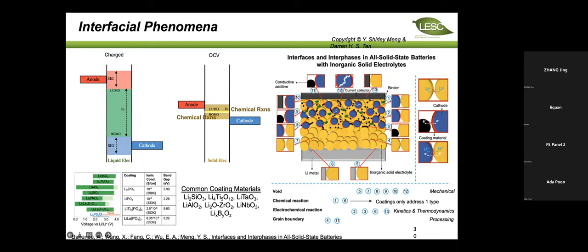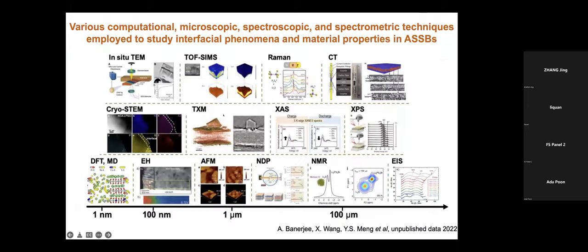interface. So in our Chemical Reviews paper, we pointed out solid state is more complex. You have more interfaces to deal with than liquid, because in the liquid case, there's no void. It will be filled by wet electrolyte. But in the solid state, in the case of argyrodite, we showcase that in fact, it's extremely difficult to maintain both chemical and electrochemical stability. So all the cathode materials have to be coated.